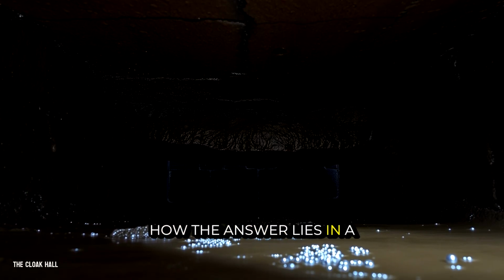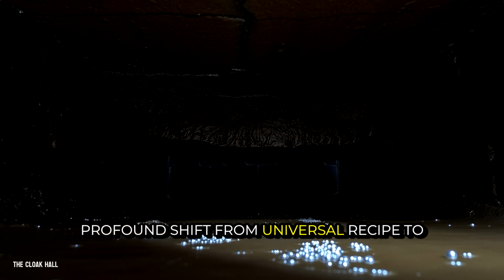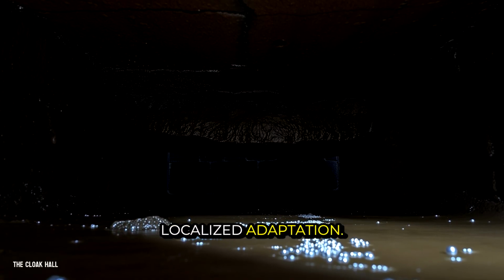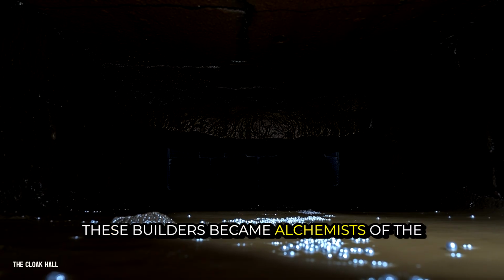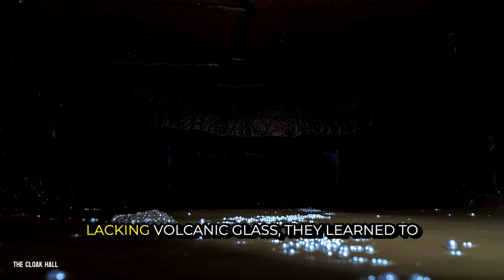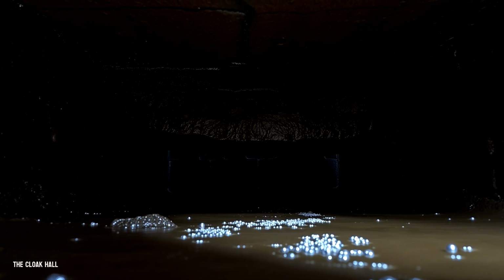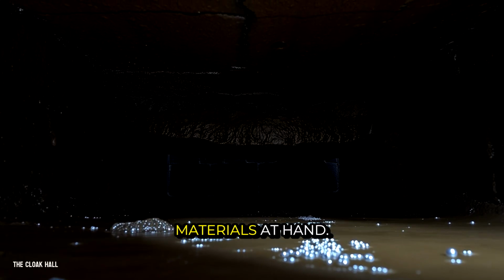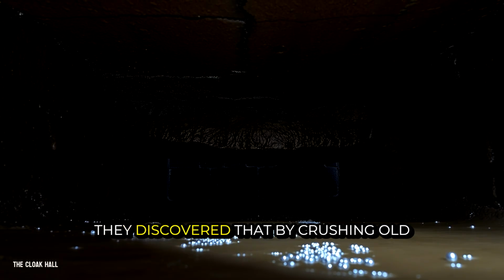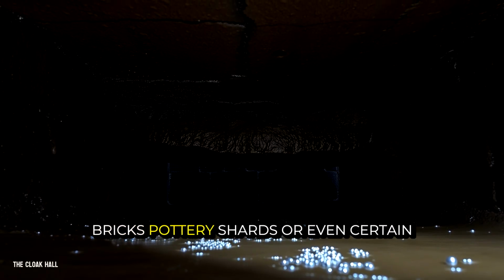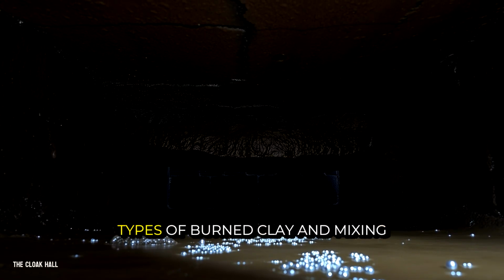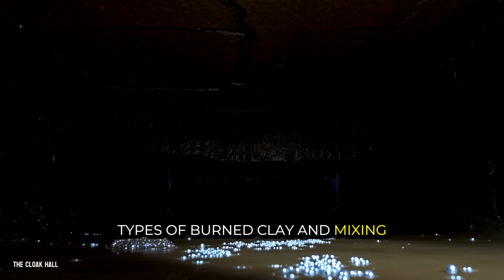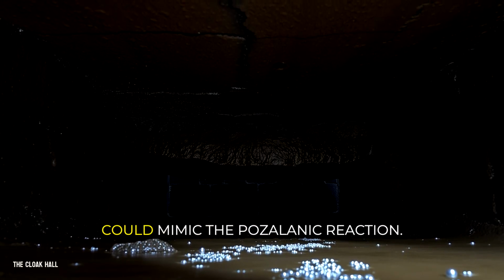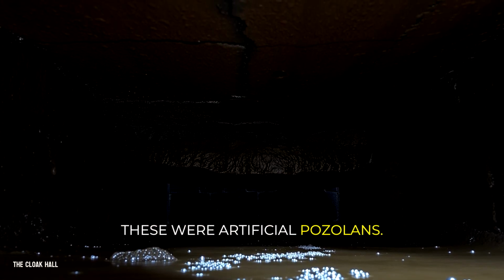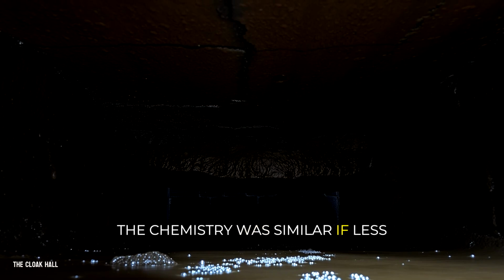How? The answer lies in a profound shift from universal recipe to localized adaptation. These builders became alchemists of the commonplace. Lacking volcanic glass, they learned to create its reactive properties from the materials at hand. They discovered that by crushing old bricks, pottery shards, or even certain types of burned clay and mixing them into their lime mortar, they could mimic the Pozzolanic reaction. These were artificial pozzolans. The chemistry was similar if less potent.